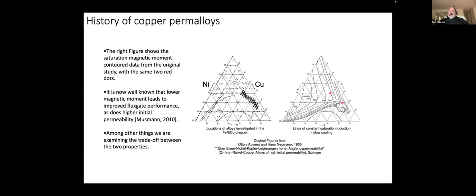This figure on the right, the triangle, shows the same red dots in the same left triangle, but now I'm showing the saturation induction that was contoured by Auwers and Neumann, and the red dots again show the range of values over which we're likely to find interesting properties, from about 600 millitesla down to about 200 millitesla saturation induction. And again, you can see it falling off fairly quickly as iron disappears from it, and getting into strange properties over here as you get into the segregation zone.